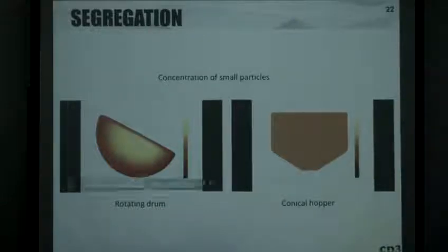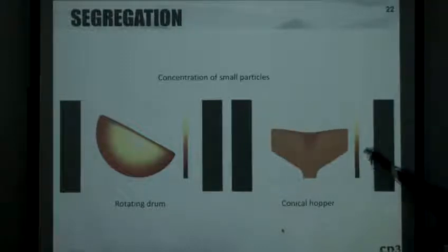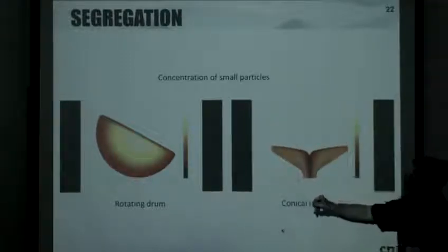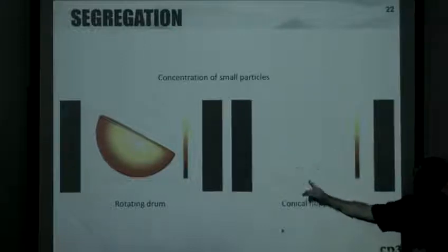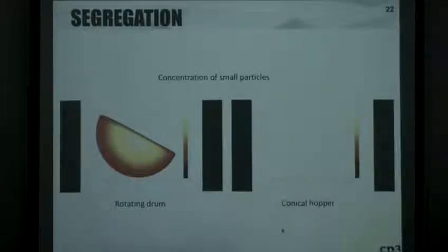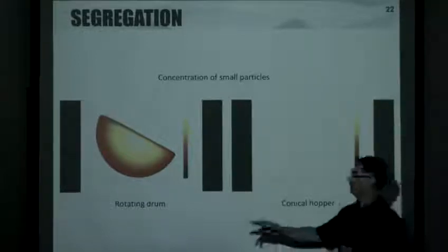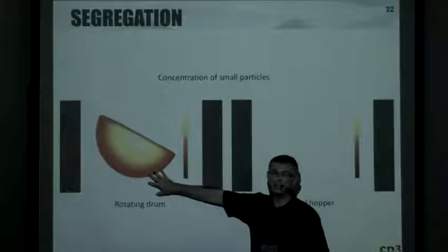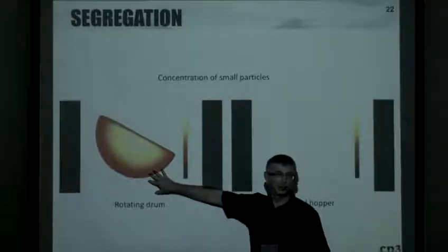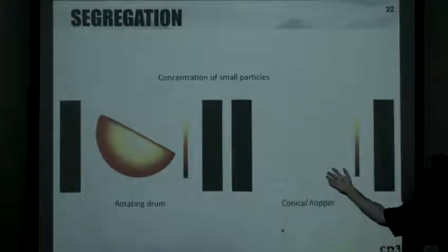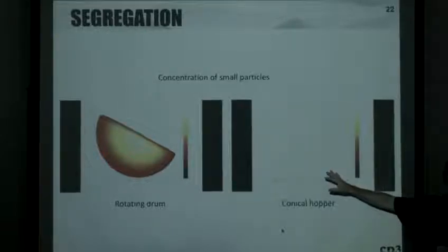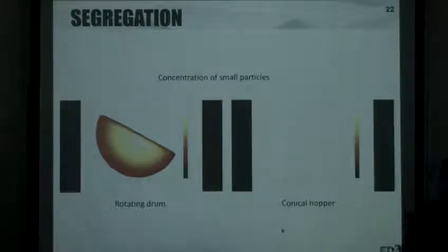We also did a conical hopper. This is an axisymmetric hopper. On discharging, you see a collection of coarse particles on the top, and they come discharging out, and at the very end you get some fine particles that come out. We did those two geometries because the Northwestern folks had done DEM simulations of that, so we could compare against it. And then a former student of mine, Bill Ketterhagen, did some experimental work in hoppers with two different size spheres, glass beads. So we wanted to compare against his data.